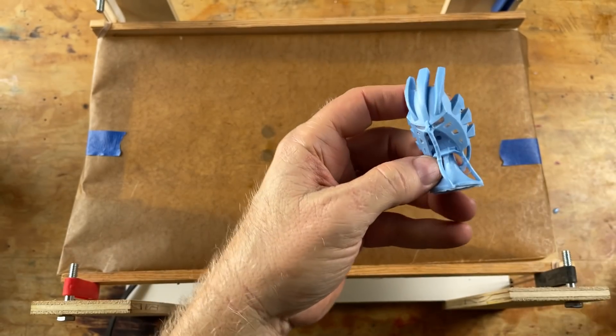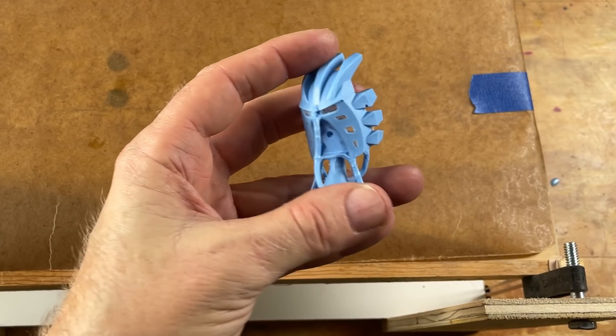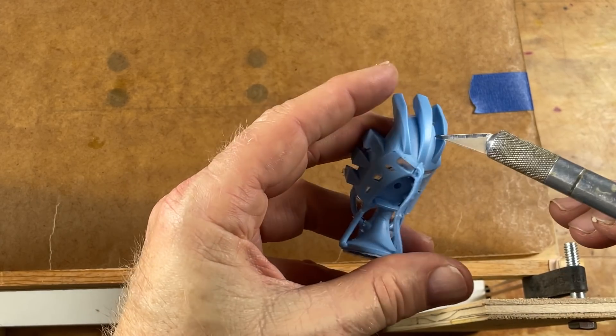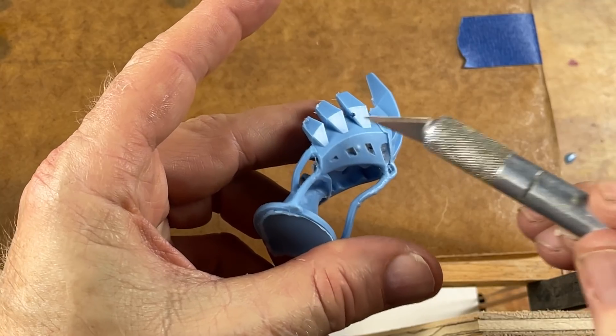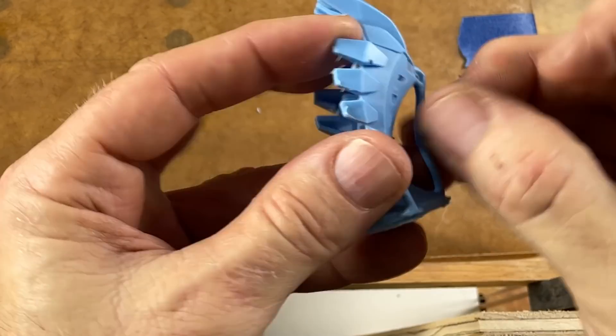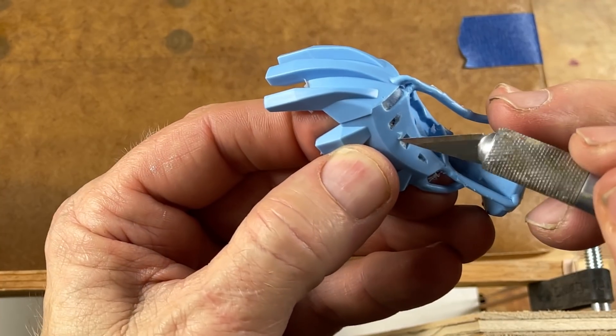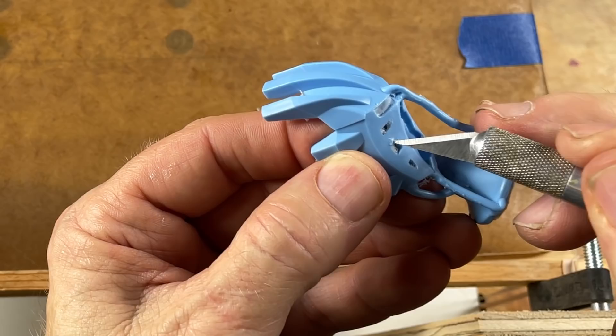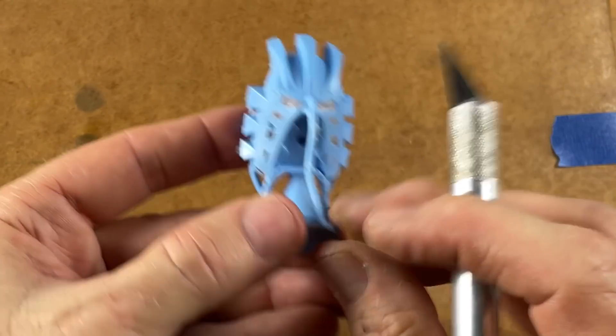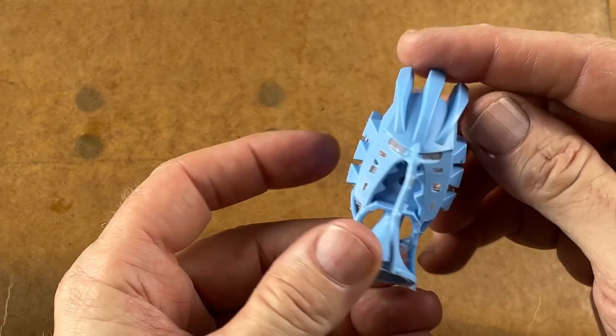Let's see what we got. Wow, this thing is just fighting us every step of the way — it has with every casting. Nice wicked bubble there. Super nice wicked bubble there. Hidden buried bubble right in there. Looks for all the world like a blister, like a bubble. Yep, it's a bubble. Injection molding can do things that resin casting can't. Conversely, resin casting can do things that injection molding can't. It's really all about the shape you want to cast.